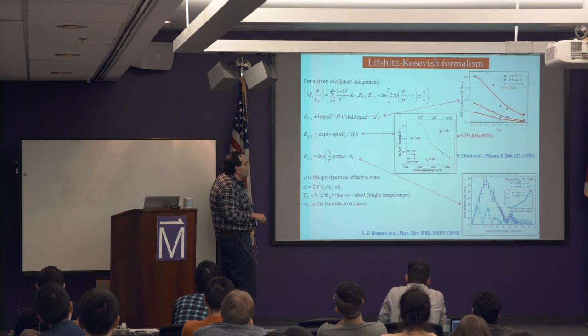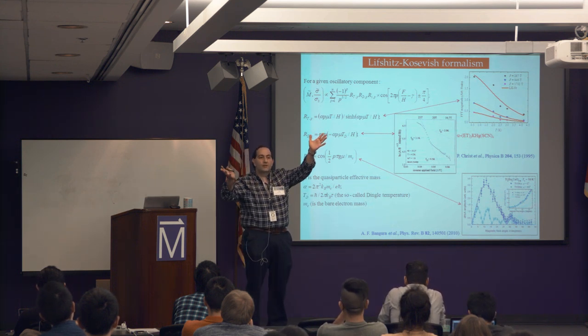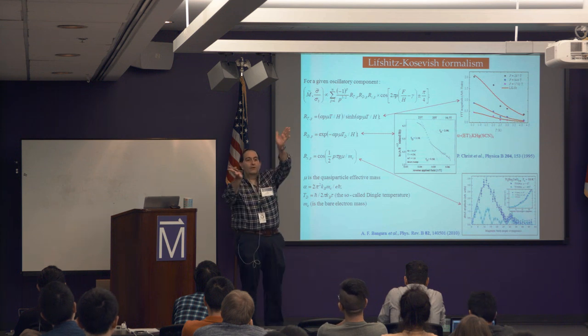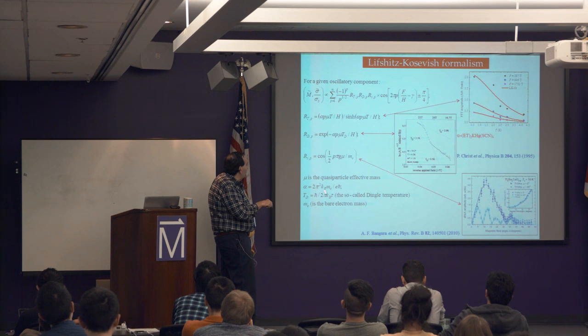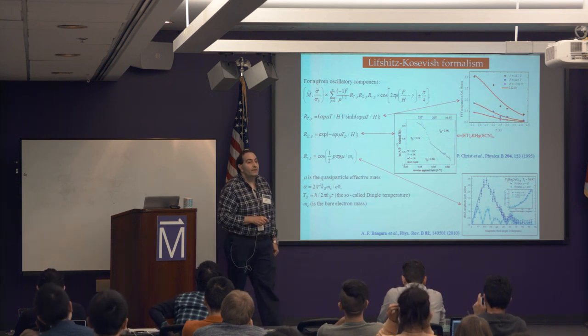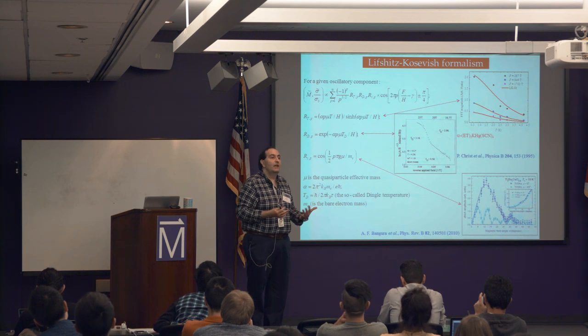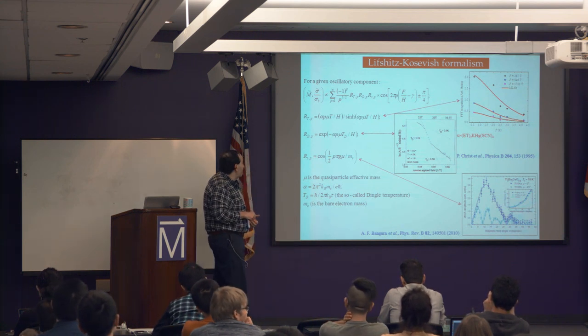There's another effect which has to do with impurities. If you have impurities, you have to go to higher and higher fields to see quantum oscillations, and they grow quite quickly. This is called the Dingle term. And the Dingle term is associated with the so-called quantum lifetime of the quasiparticle. So you can measure the quantum lifetime by looking at how these oscillations grow with the magnetic field.